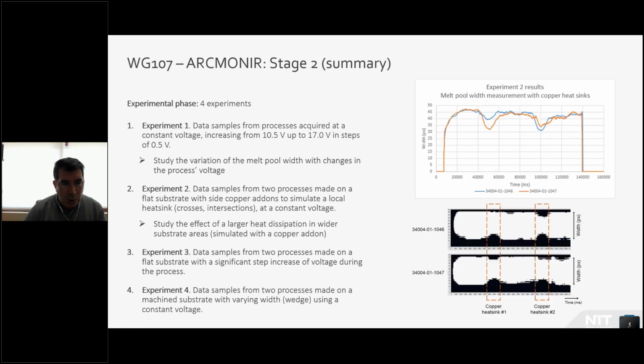Then we made a second experiment in which we used a sample with 2 copper heat sinks on the sides, so that we can see the effect on the melt pool width as the process passes next to these areas where there is a larger dissipation of heat.